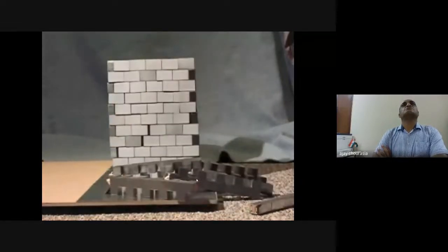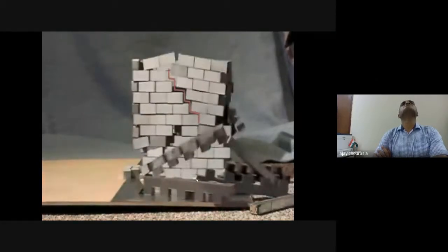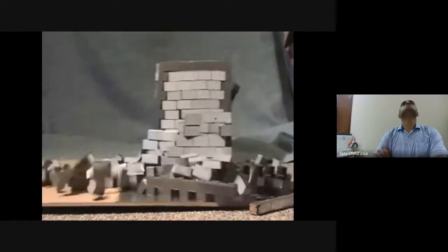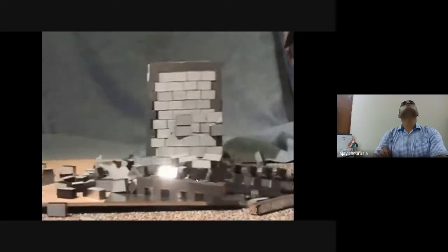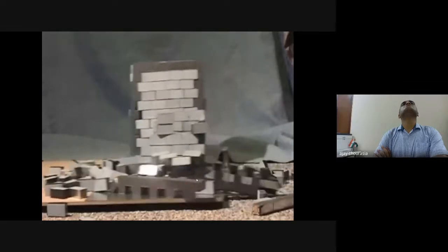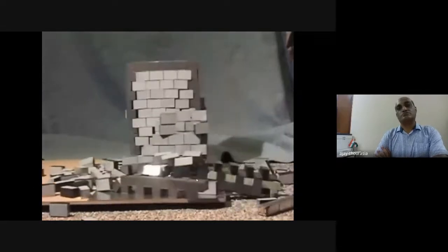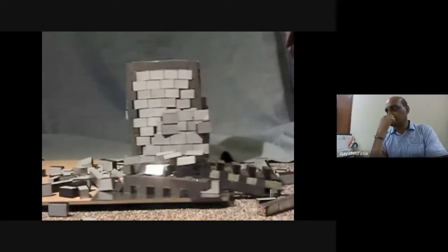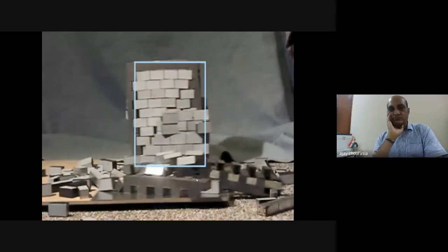In the unreinforced masonry system, we see diagonal cracks forming, shortly followed by the complete disintegration of the masonry wall. In the confined masonry system, we also see diagonal cracks forming in the wall. As the wall deforms, these two corners pull apart from each other, causing tension. As we know, masonry alone is weak in tension. Similar to the unreinforced masonry system, we see cracks develop. However, the confining elements postpone the complete disintegration of the wall.